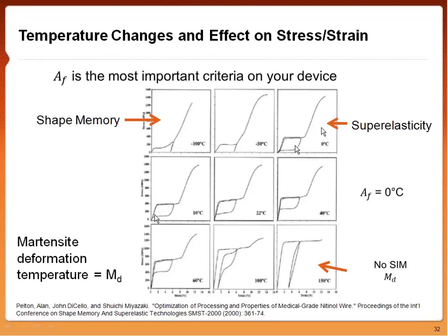And we see as we raise the temperature more and more, we're raising our stress plateau until a point where, again, that non-transforming austenite graph comes back into play. We see it reaches a point where we can no longer stress-induce a phase transformation, a stress-induced Martensite in the material. And this is called the Martensite deformation temperature.